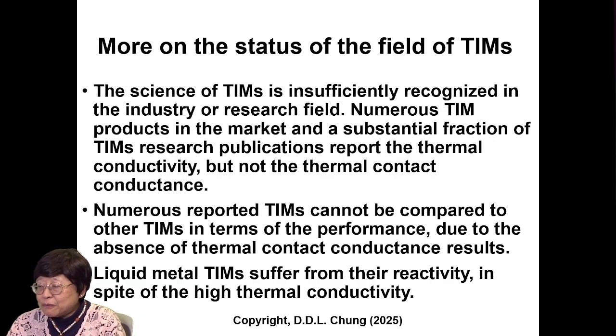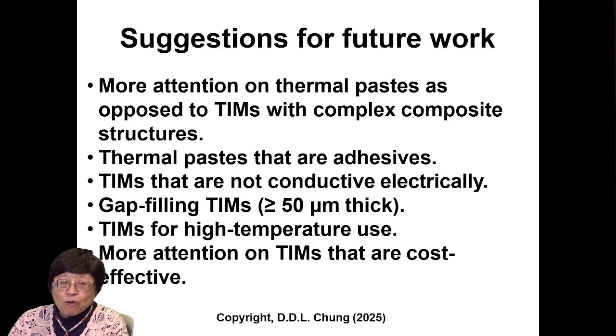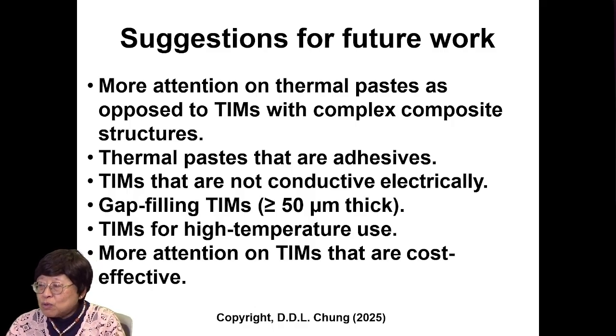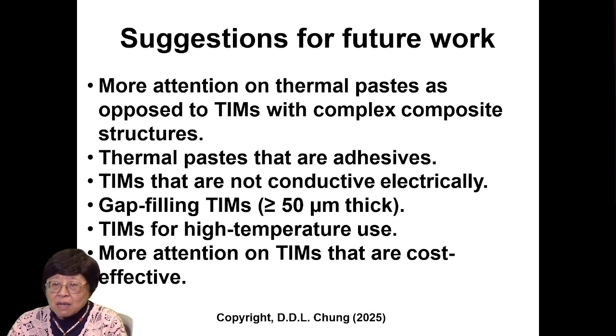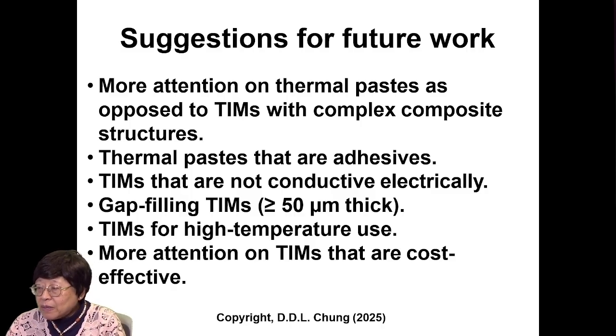Liquid metal TIMs suffer from their reactivity in spite of the high thermal conductivity. Suggestions for future work: more attention on thermal pastes as opposed to TIMs with complex composite structures. Thermal pastes that are adhesives, TIMs that are not conductive electrically, gap-filling TIMs with thickness exceeding 50 microns, TIMs capable of high temperature use. More attention on TIMs that are cost effective.